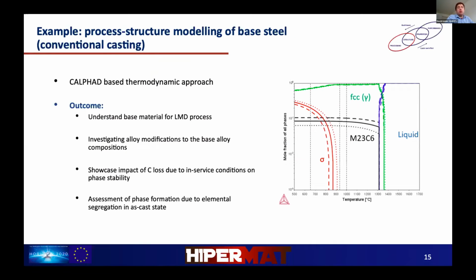Examples of how one could move along modeling these things is the same plot as shown by Fernando. Just want to show how one can use it to understand the influence of composition on phase formation in the benchmark material or in the standard material here. And as Fernando already mentioned, full lines is for one composition within the specification, and the dashed and dotted lines are for other compositions. And specifically, this is focused on carbon content, where you can see the red lines for low carbon content. It's the dotted line where the sigma phase forms at around 900 Celsius, whereas for the high carbon content is the dashed line where the sigma phase formation temperature is significantly lower.